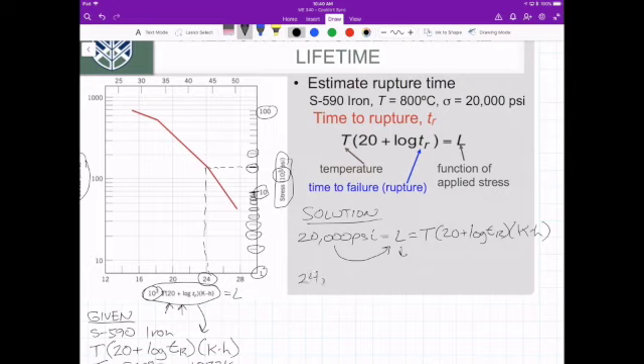So we use our L value, 24,000, and that equals our known temperature, 1073, times 20 plus the log of the rupture time. Okay, so with that, we can solve for the rupture time. When you do that, I get 233 hours. Okay, like I said, this is in hours, not seconds like diffusion. This is for 800 degrees C.